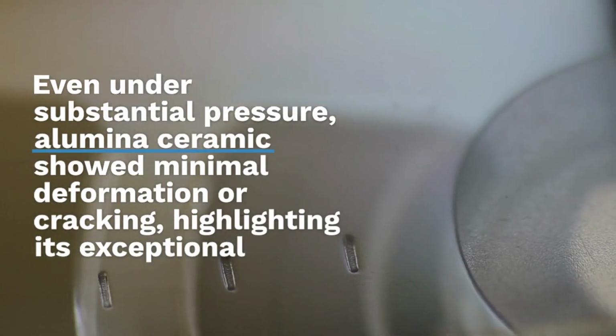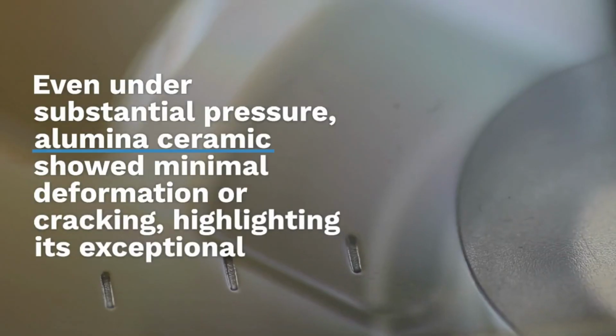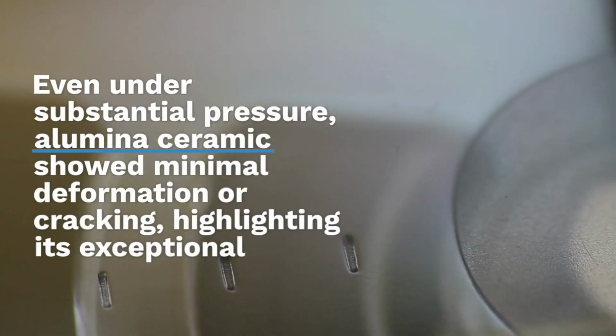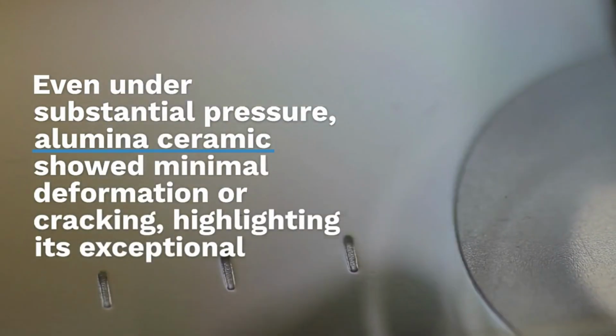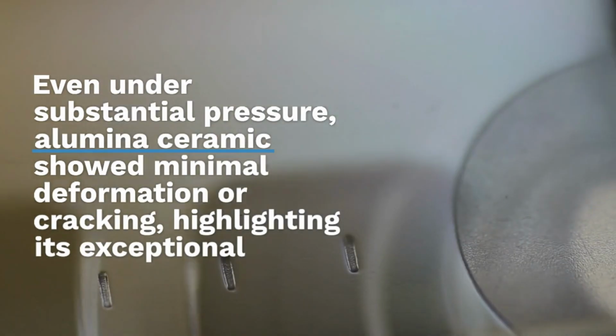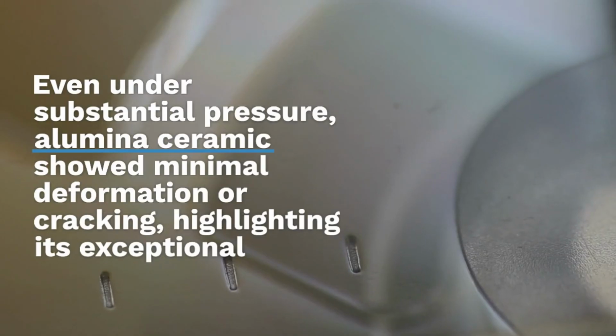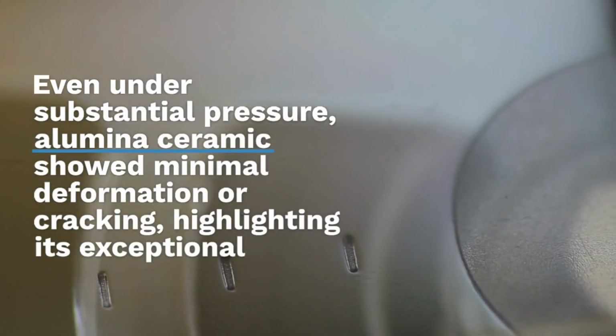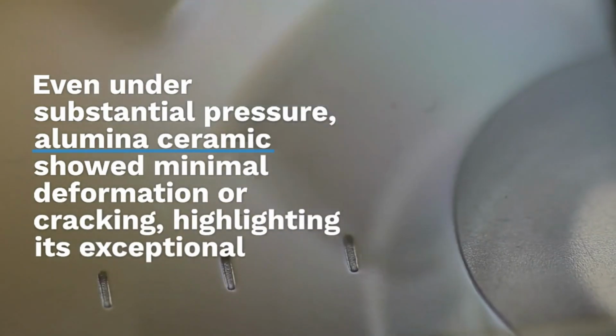In addition to its resistance to extreme temperatures and chemical exposure, alumina ceramic furnace tubes were subjected to a mechanical stress test. This test involved applying significant pressure to the tubes to assess their mechanical strength. Remarkably, even under substantial pressure, alumina ceramic showed minimal deformation or cracking, highlighting its exceptional mechanical stability.